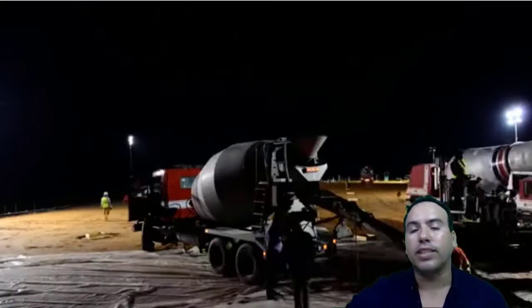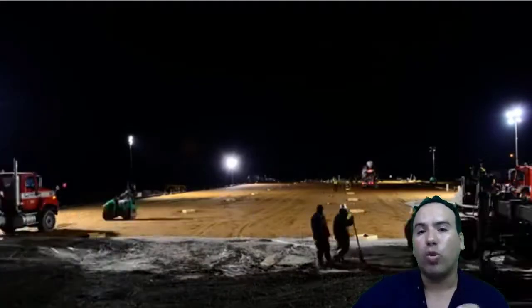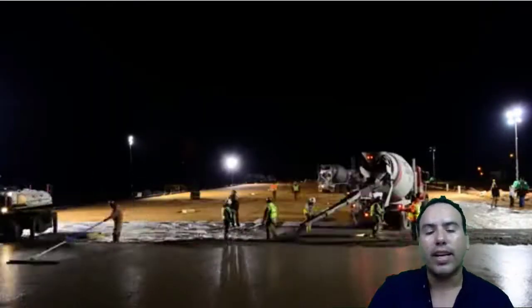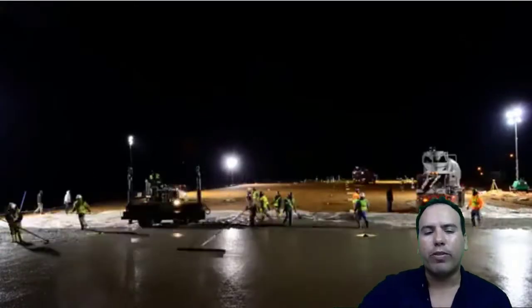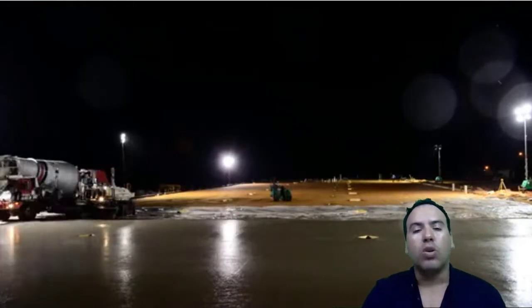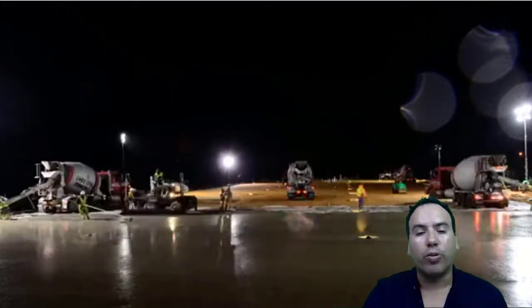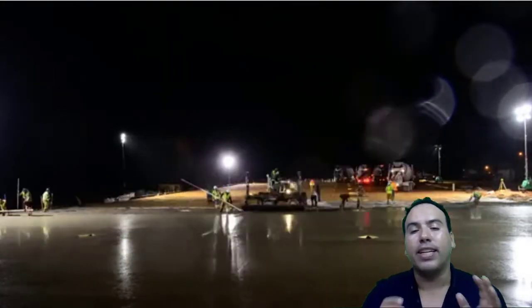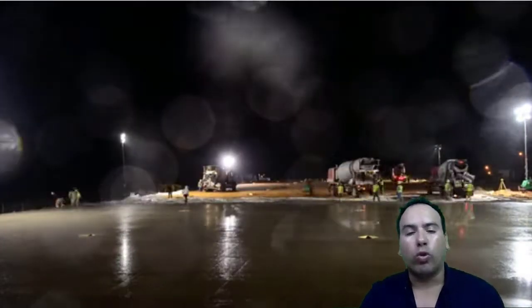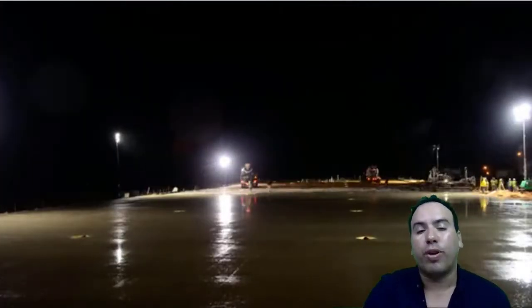If you want to check: after 1 day it is about 16%, after 3 days 40%, after 7 days 65%, and after 14 days 90%. But what happens after 28 days? It becomes 99%. So from what I just said, it's clear that concrete gains strength rapidly in the initial days after casting, thus 90% in only 14 days, and it reaches 99% in 28 days.